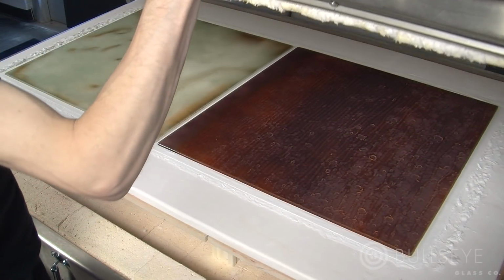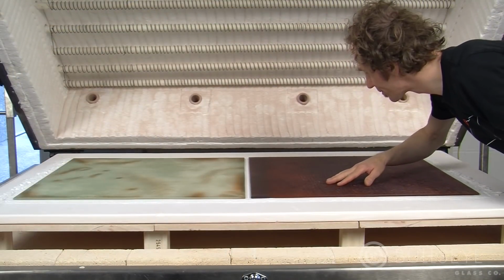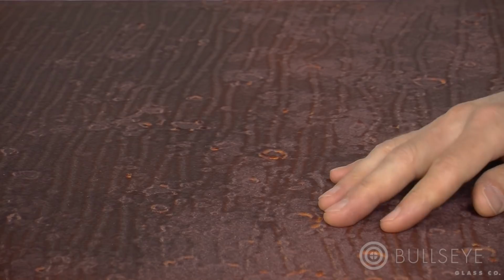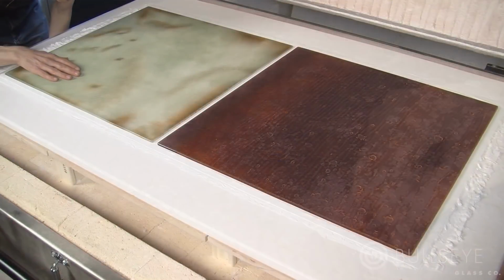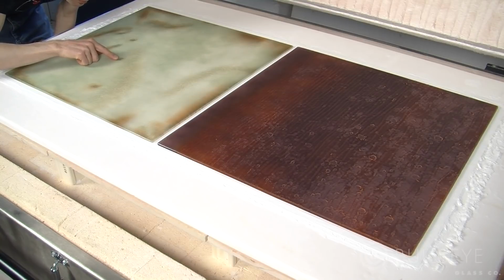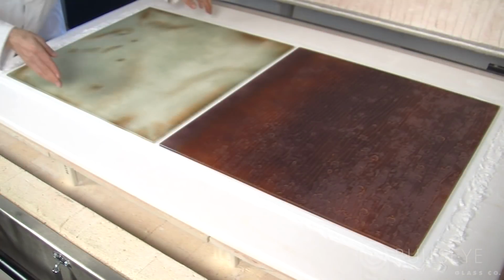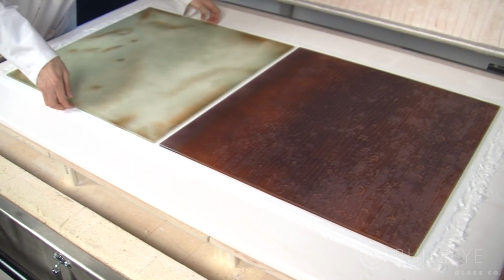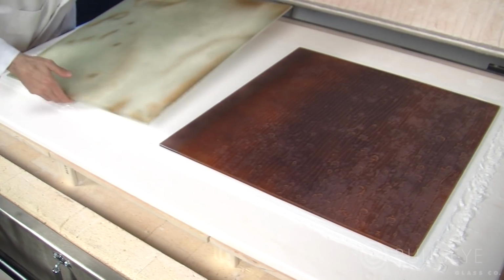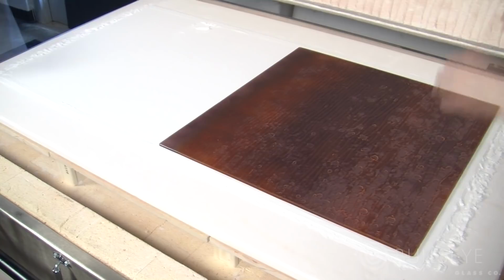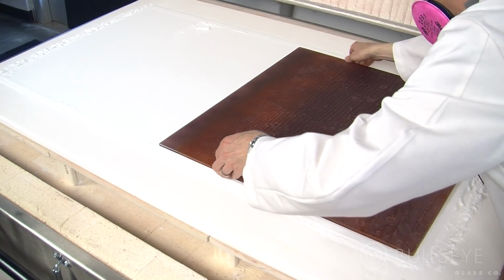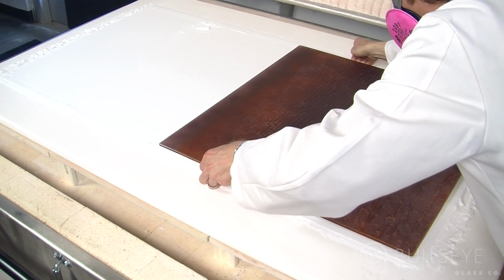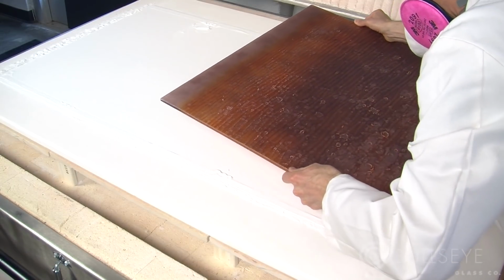And the first thing that I'm going to do before I try to take anything out is just review the texture, the color, see if there are any surprises. Feel that surface. And then, because I can't use a suction cup on the surface, I actually have to lift it out by getting my fingers under it. And I'm trying to do it without disturbing the fiber paper underneath it too much. And there you can see that I'm wearing a respirator. That's because all of that thin fiber has basically turned to a powder that becomes easily airborne.